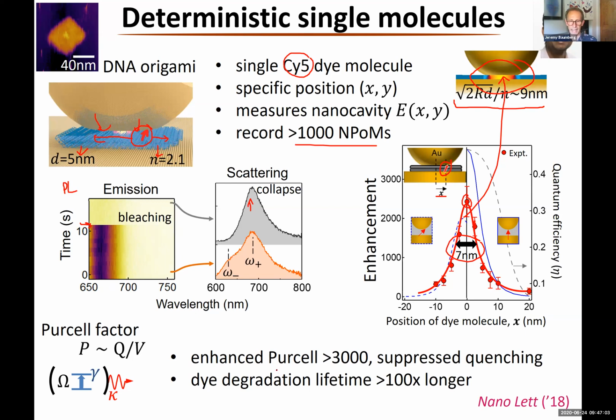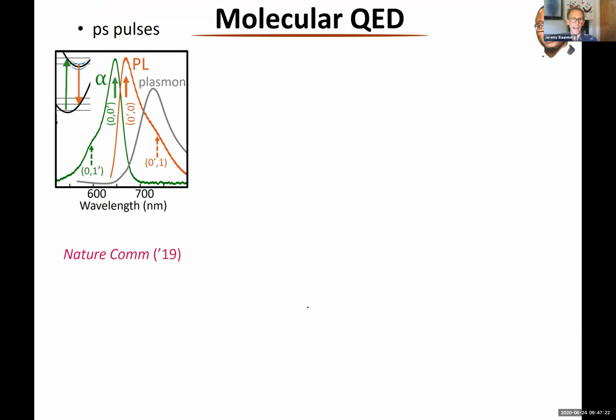We can also see the enhancement of the Purcell factor, but it actually, it's already over 3,000. And in fact, the dyes emit far more photons than they normally would here. They go around an emission event much, much faster. So it's more difficult for them to be quenched in the system. So you can look at this paper if you want to see some more about that.